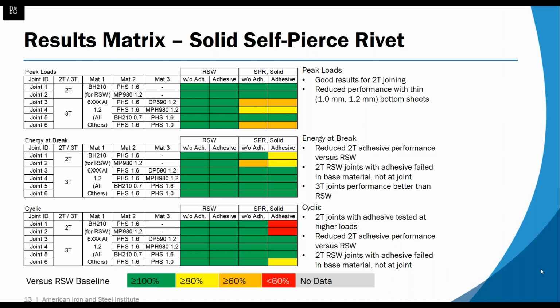Starting with the peak load results, what we found with the solid self-pierce rivet, the quasi-static peak load was directly comparable to the resistance spot weld in the 2 thickness joints. So those results are green.